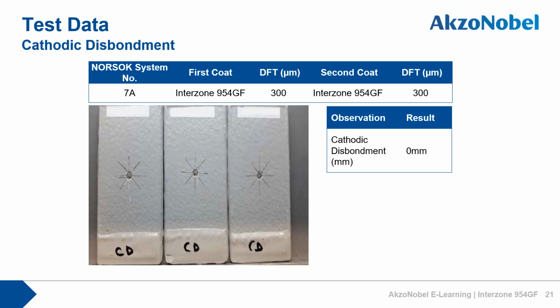Here are some panels that were put through the cathodic disbondment test. Again, Interzone 954GF has shown extremely good performance with zero disbondment. And this is an important test to prove compatibility with cathodic protection, which is often required in immersion conditions.